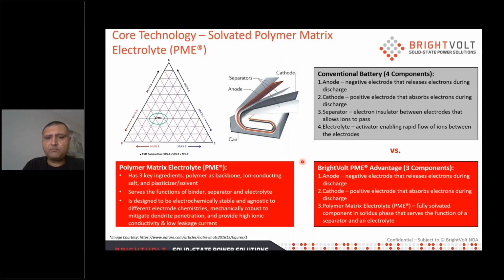And so when we start preparing, and I'll speak a little bit more about this on the next slide, when we start preparing our PME, it's in the form of a solution or a gel with a viscosity that's very similar to what you would have in a conventional lithium-ion slurry. And so we start with mixing our PME in the slurry in place of the conventional binder that you might use. So there's no need for an additional binder.